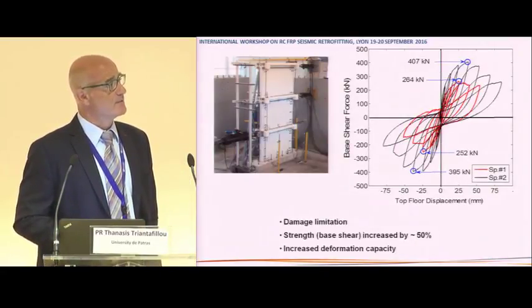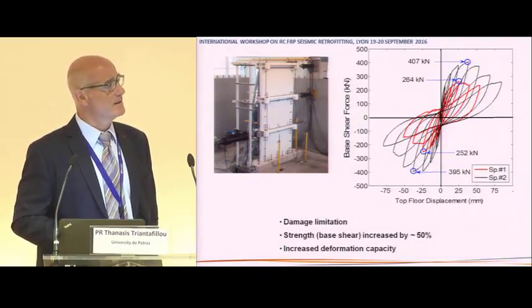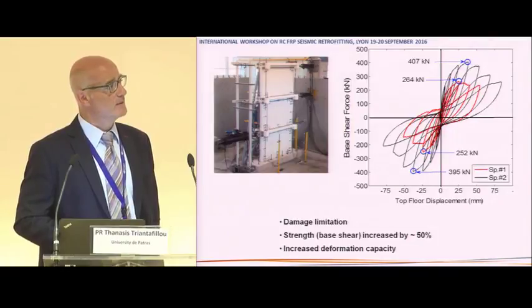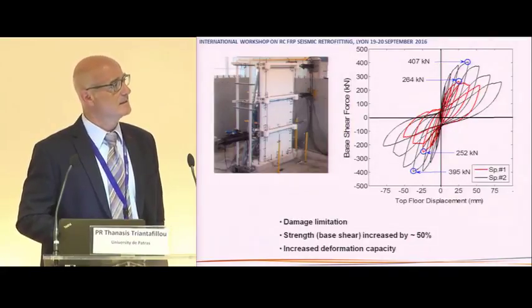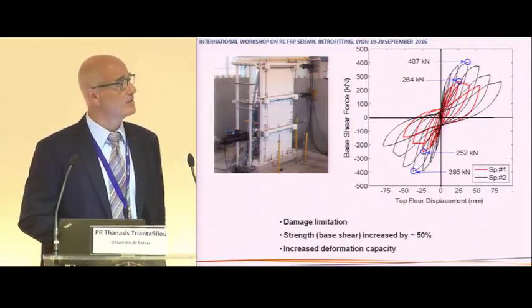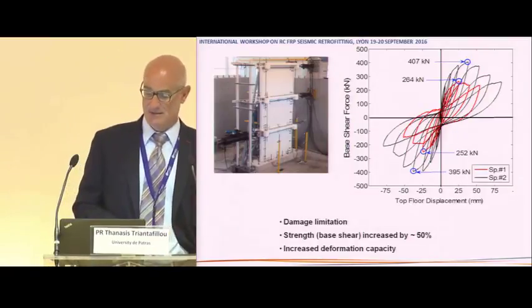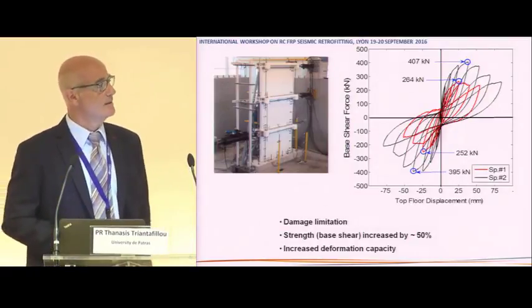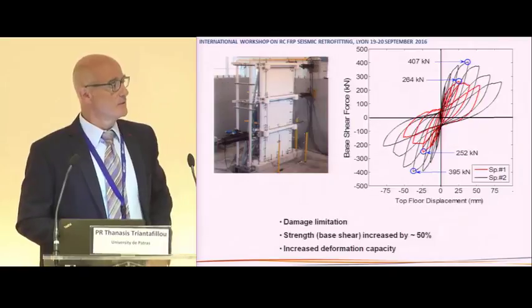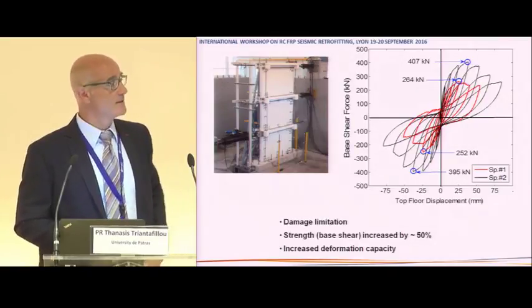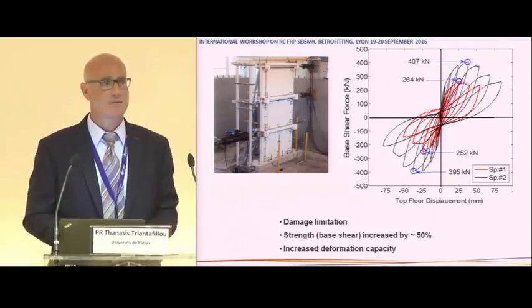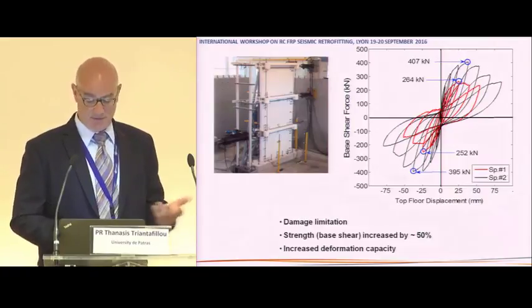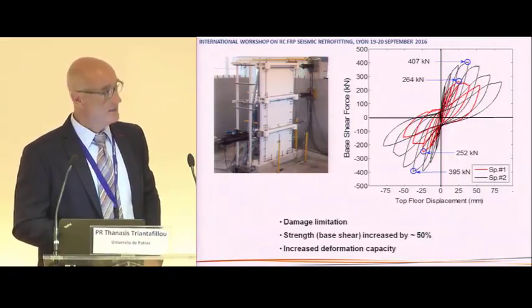With red, you see the response of the frame without this strengthening solution, and with black, you see the response of an identical frame retrofitted with the TRM system. The damage was reduced substantially. The strength was increased by more than 50%, and the deformation capacity by about the same amount.